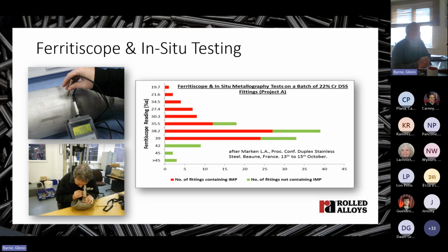Now, typically these steels contain about 50% plus or minus 10% of each phase, so ferritoscope readings below 40 are a concern, and the lower the reading, the more concerned you should be. But this technique is prone to give some false positives or false negatives, whichever way you're looking at it, particularly over this intermediate range of readings. Generally, very high ferritoscope readings mean the fittings don't contain intermetallic particles. In this intermediate zone readings, some do and some don't. But generally, as the numbers get lower, there's a much higher probability that the parts are actually sensitized.